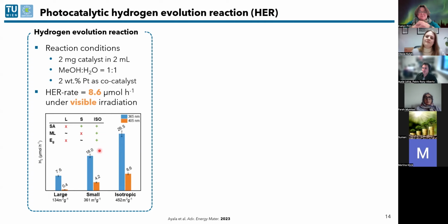This is because you need enough so that you can extract all the charges. But if you have too much, you also start blocking the light. So too much platinum is not good. And from an economic perspective, I would say it's probably better if you can reduce the amount of platinum that you're using. This is also why at my master's, I was trying to go into single site photocatalysis, so really reduce the size of these particles to the atomic level. But this is also pretty challenging.